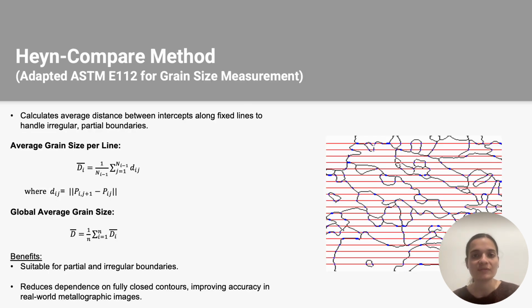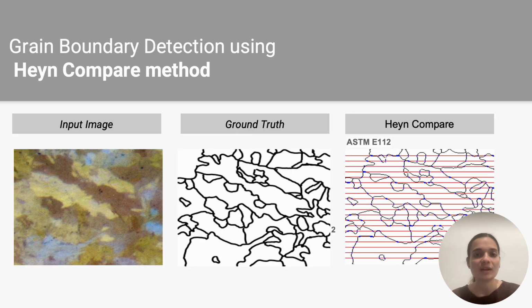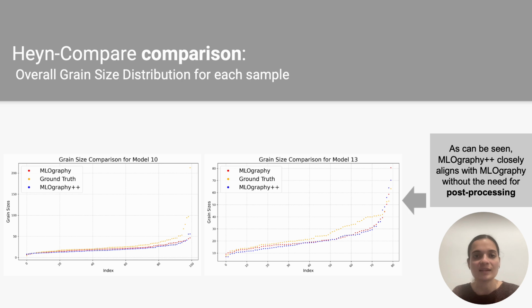We use a variation of the Heyn intercept method called the Heyn compare, which calculates average distances between intercepts along fixed lines. This approach improves accuracy for irregular and partial boundaries, reducing reliance on fully closed contours in real-world images. Here you can see the Heyn compare method applied to a cropped image from the TBM dataset using horizontal lines to measure the grain boundaries. These graphs show the grain size distributions for the individual samples using the Heyn compare method. They highlight how MLography++ closely matches MLography and the ground truth, all without requiring post-processing.